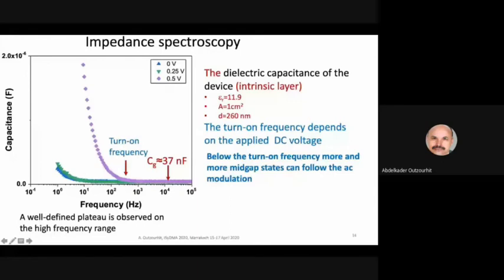So this figure is for the 0.5 volts forward bias, and the green one here is for 0.25 volts, and the blue one here is for the unbiased solar cell. And as you can see, this turn on frequency is a function of the applied bias. Again, below this frequency here, more and more mid-gap states or deep states within the band gap of the hydrogenated amorphous silicon are able to follow the signal or the AC modulation.